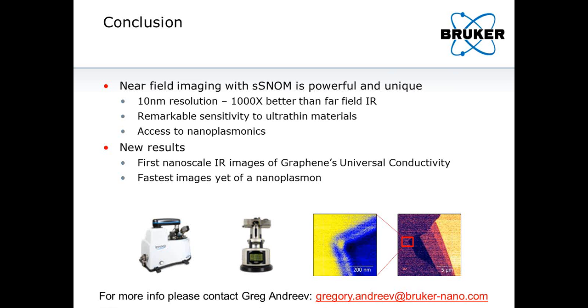If we have a method that can confirm that very quickly, it can potentially be useful in combination with other methods. I'd add that in few layer graphene, if you have a few layers, each individual layer may truly change the properties, so it's important in research. Also, in more scalable graphene production, it's hard to make consistent graphene with a consistent number of layers or low defect density. So I think it's generally always important to know.